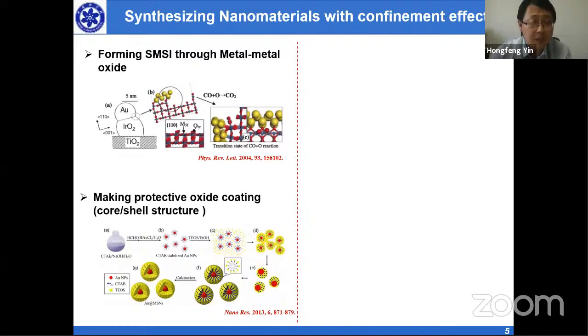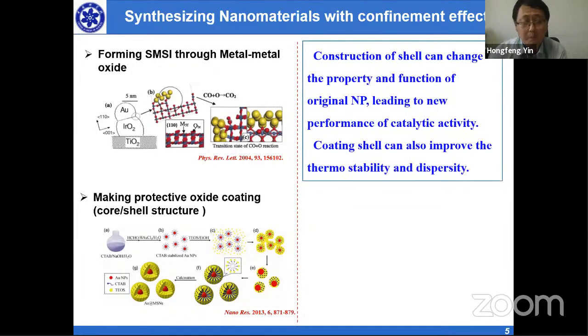Another way is making a protective oxide coating in the form of core-shell structure. For example, we have pretty small gold nanoparticles, and we coat them with a pretty stubborn silica or zirconia shell. Then it will form a cage to prevent the gold nanoparticle from aggregating at a high temperature. That's a pretty good way. So by constructing the shell, it can change the property and function of the original nanoparticle. That will lead to new performance of the particle in catalytic activity. Also, it can improve the thermal stability, as I just mentioned.